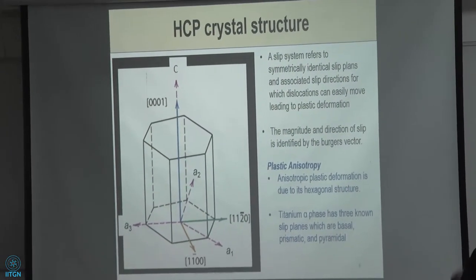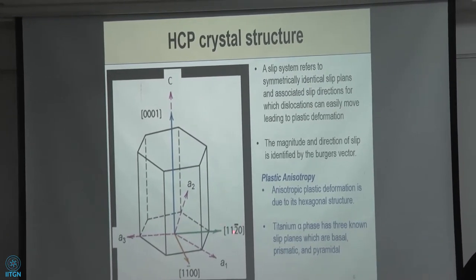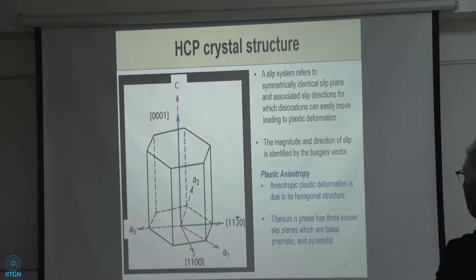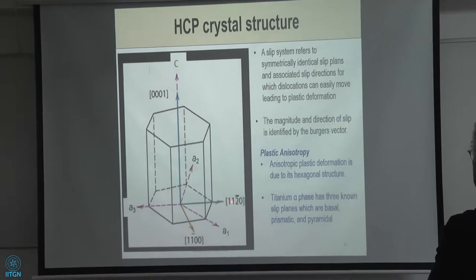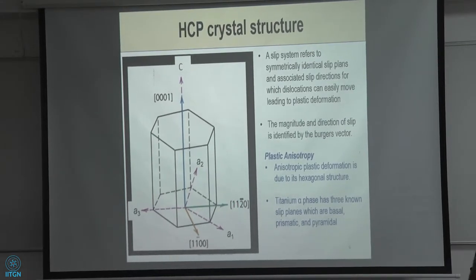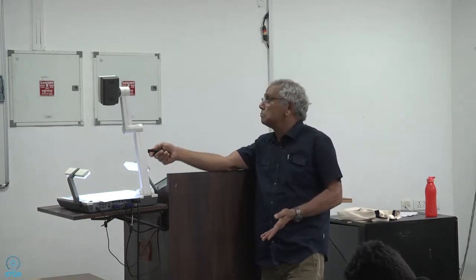And there are also a lot of micro textures. What they are finding is that there are micro regions in these alloys which are very highly textured. They're happening in locations inside the material. This is one guy from General Electric, Cincinnati, Andy Woodfield, who said that the microstructural features controlling the dwell response in alpha beta processed titaniums 6242 include size, shape, and volume fraction of MTR, micro textured regions, okay? Micro textured regions, the same thing, MTR. Okay? Size and density of primary alpha grains.